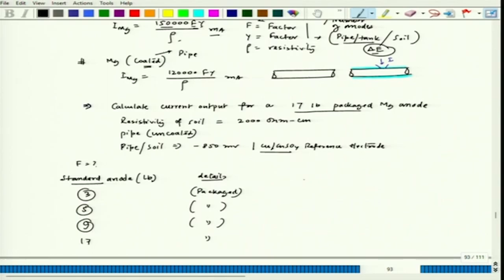Now if we try to see the factor F, in this case it is 0.53, then 0.60, 0.71, and here it is 1.0. So, F is equal to 1.0 from this table. This table is a much longer table. You can refer to Principles of Corrosion Engineering and Corrosion Control by Zaki Ahmad. If you follow that book in the cathodic protection segment, you can find these tables.